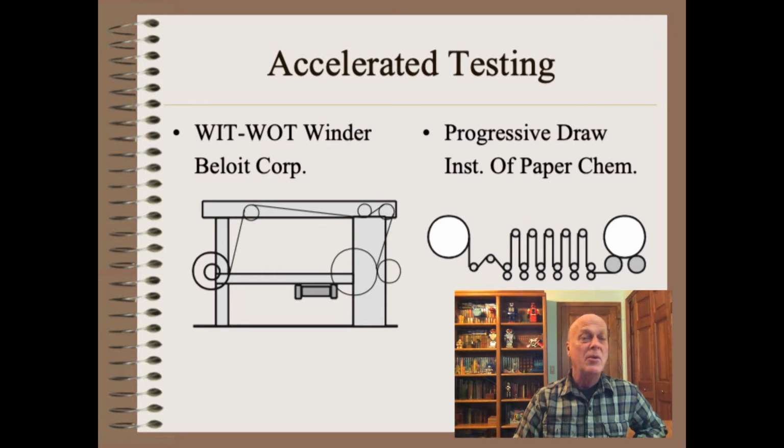Both of these rewinders are ways to do accelerated testing. Instead of running normal tensions and needing to wait for many rolls to find your first break, we run much higher tensions and get many breaks per roll. Thus, breaks are conveniently frequent for testing. Not too many, not too few.